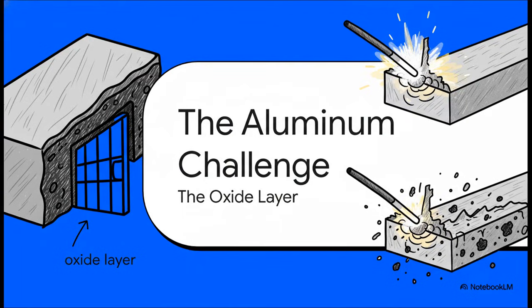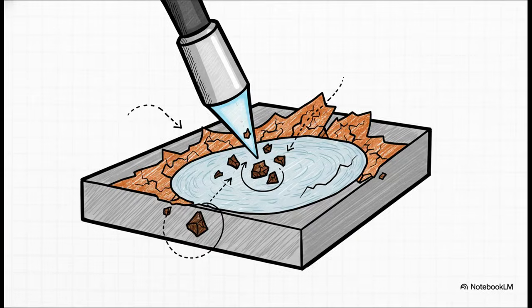You know, when it comes right down to it, the biggest, most important hurdle in welding aluminum is beating that oxide layer. It's the gatekeeper. It's what decides if you end up with a strong, perfect weld or a weak, contaminated disaster. See, this oxide layer doesn't just get in the way. It actively tries to ruin your weld. If you just melt the aluminum underneath it, little flakes of that tough oxide can fall right into your molten puddle. These trapped bits, or inclusions, are basically like having tiny pieces of sand in your weld. They create weak spots that can cause the whole thing to crack and fail later on. You have to get rid of it as you're welding.